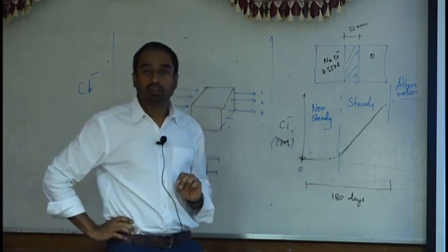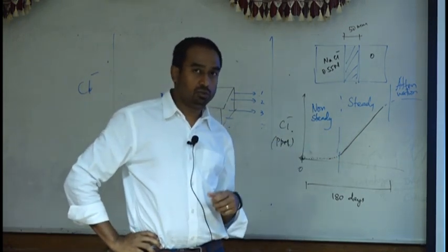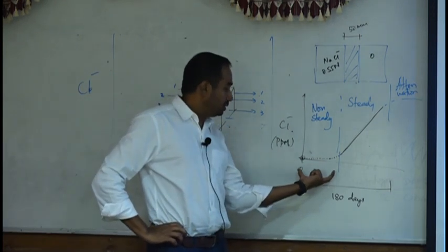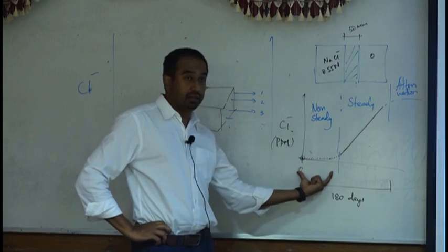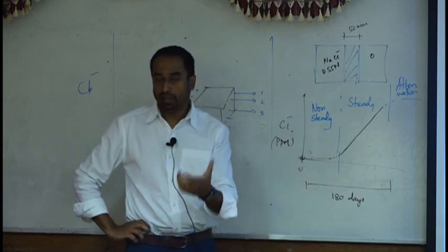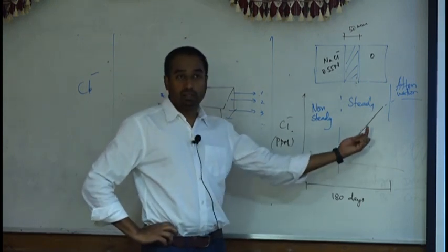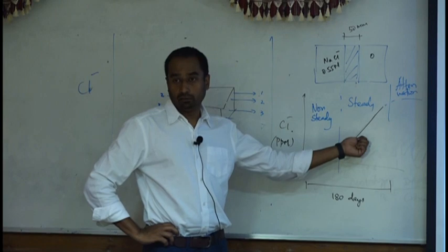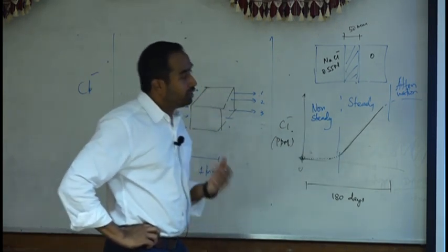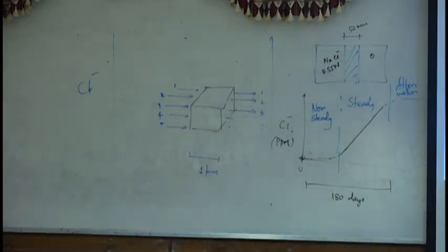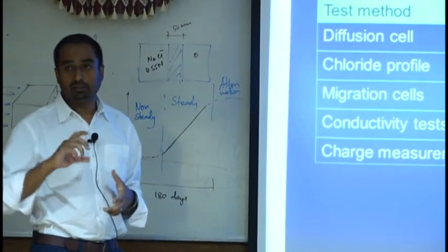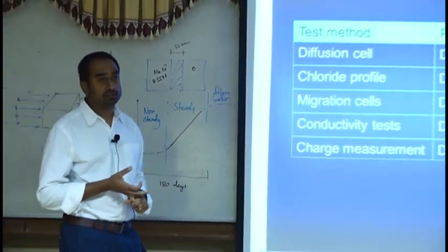And you won't be able to correlate them directly. You can correlate them indirectly. If you quantify the reaction phase of it and add it to the value that you get here, I don't mean simply add it, then you'll be able to get the coefficient which you're getting here. And there's a lot of work that has happened in that area. So we now know that I can relate this and this together using quite a nice equation, but it needs a few values like porosity and binding capacity.